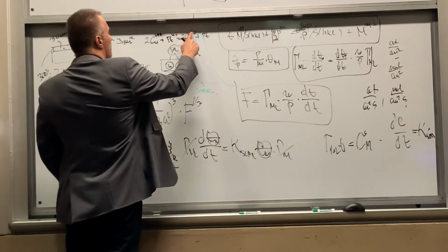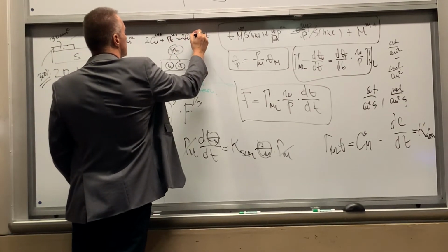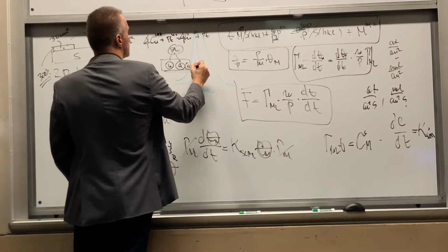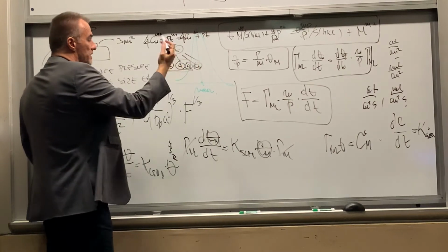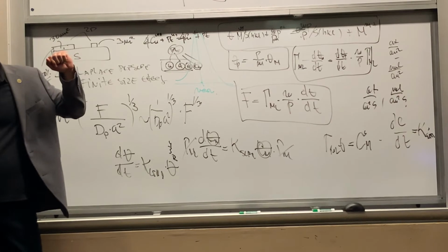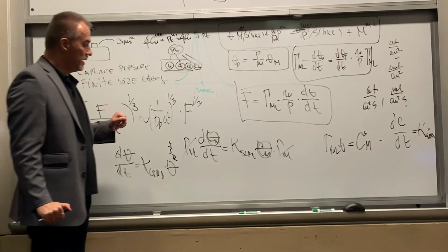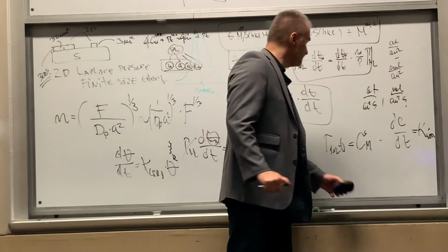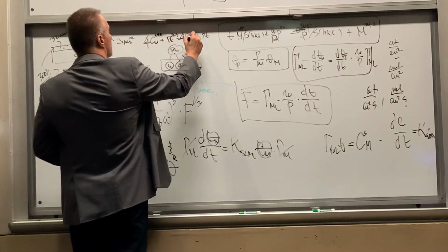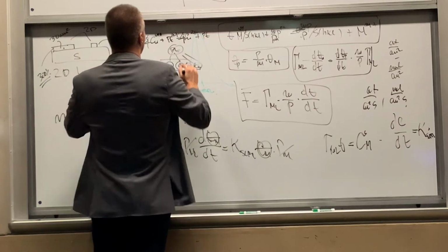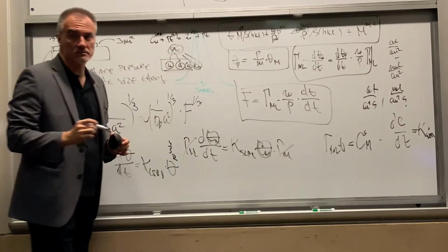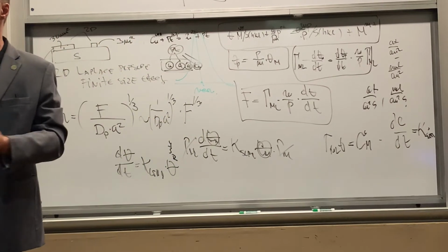If this would be a copper 1+, so copper plus, then I would need 4 here and 4 here. That would mean I need 4 coppers. And then the reaction order would be 4 in terms of the copper UPD. Now, if I use the platinum 2+ and the copper 2+, then I would have 1 copper reacting with 1 platinum, and the order of the reaction would be 1.